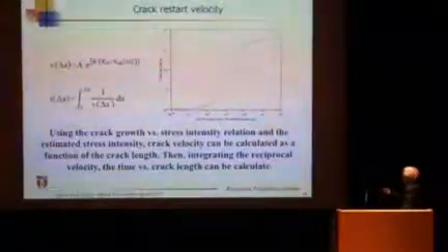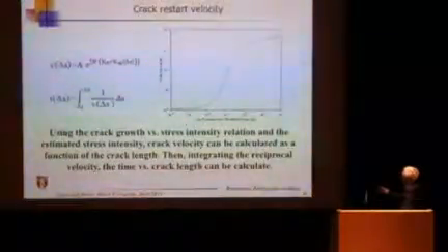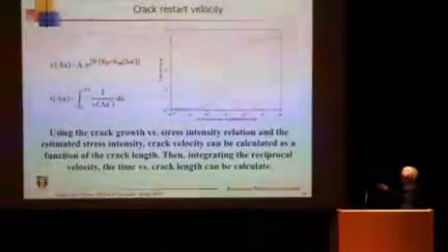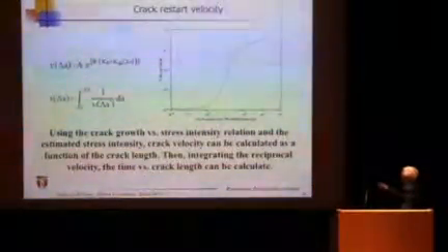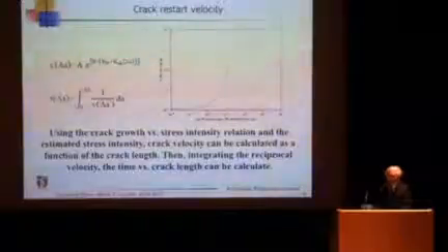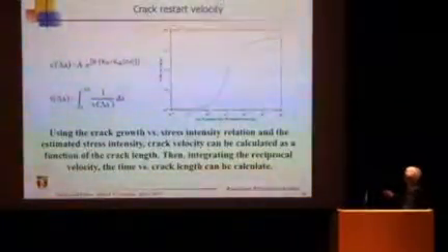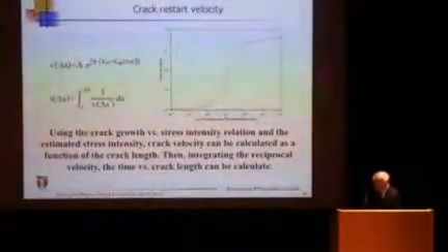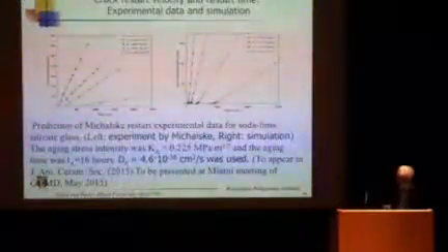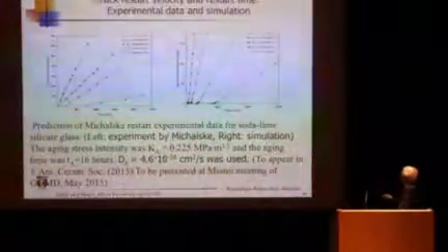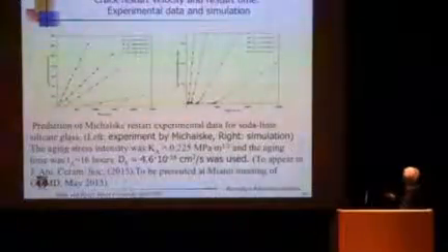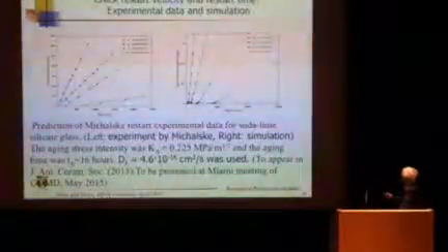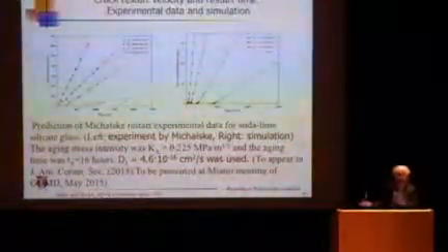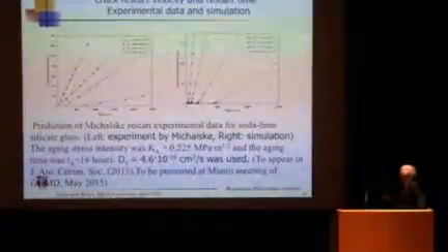By the way, this is such a small scale, 10 to the minus 10, that's 1 angstrom scale. So this 10 angstrom is a very short distance. Crack growth is very difficult, slowly growing, but it takes time. So we can calculate how long it takes to go through, and we came up with this result, that if you apply lower stress, you have to wait a long time to pass through this shielding region.